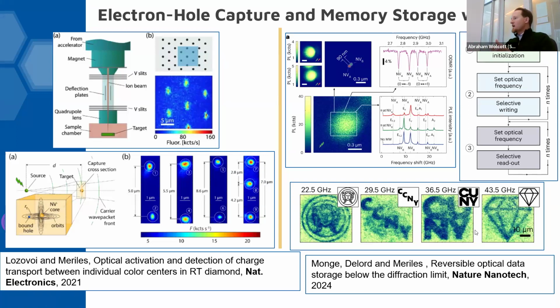And then on the right-hand side, you've got recent work for the storage, the reversible storage of information within the electronic structure of the diamond done at cryogenic temperatures. So basically you would have hyperfine splitting of the states that I showed on the last slide, and you can be able to control the NV0 and NV minus charge state, and therefore the photoluminescence, and encode information within the same plane. And I think this is an important aspect.